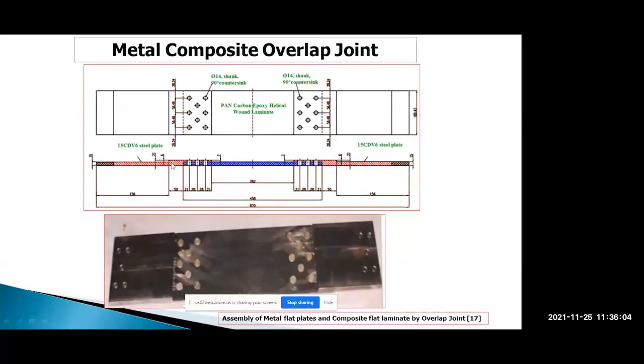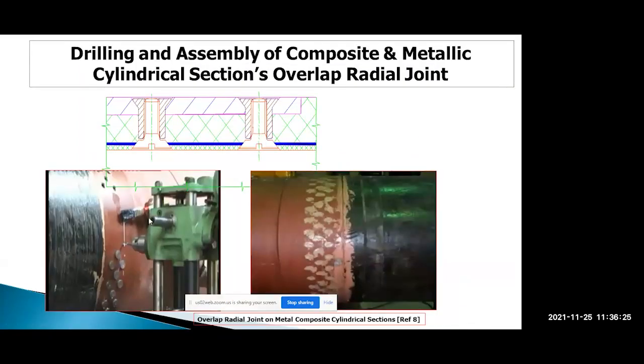In the same way, in the overlap joint, these two metallic plates are joined with this single composite plate by a radial joint. So this is the lap joint, the radial joint. Here we have to make long in situ holes in metal and composite. On cylindrical composites also we can join. Here we have to take care to do in situ drilling on composite as well as metal. And in a lap joint, the composite should always be inside and the metal outside, because composite expands more than metal. Because of the mismatch in CTE, a lot of stresses will be induced. That's why we put the FRP inside and the metal outside. So this is the joint, where we made in situ drilling. These are all about joints.